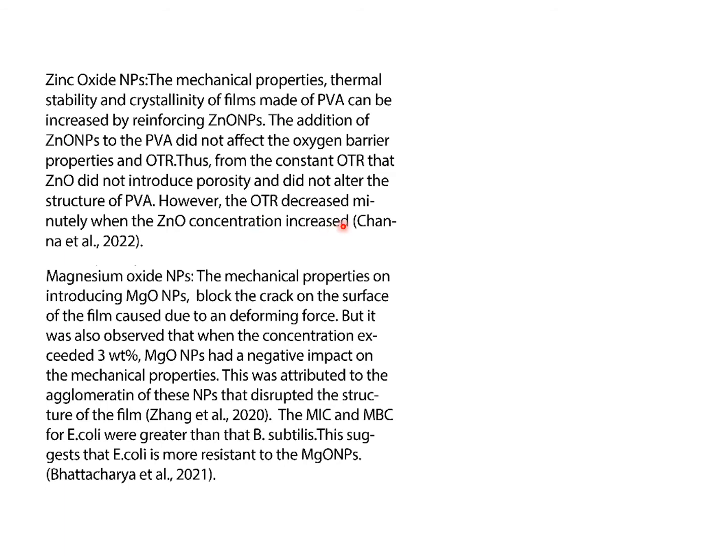It was noted that the oxygen transmission rate of PVA films before and after introducing zinc oxide nanoparticles remained the same. So the porosity that we can control has not been altered. But it is also important to note that the oxygen transmission rate decreased to a minute level when zinc oxide concentration was increased.